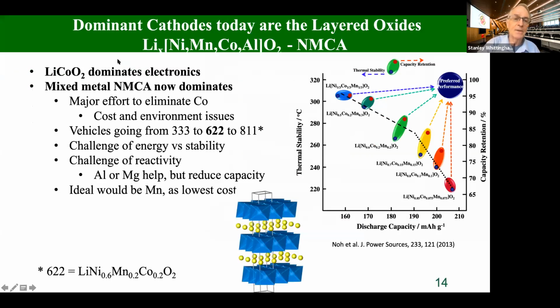So let's look at the cathode now. And as I mentioned earlier, most of the materials used today are these layered oxides. They replace the sulfides. And they have essentially one lithium in them, the common ones. Then they have a mixture of elements, typically nickel, manganese, cobalt, and invariably a little bit of aluminum to stop you charging these all to the +4 state, these stabilizers and materials. And you'll see this lettering here, NMCA, commonly used. The pure cobalt analog is in most of your electronics, but the mixed metal ones dominate everywhere else. And today there's a major effort to eliminate the cobalt, both because of cost and environmental issues.